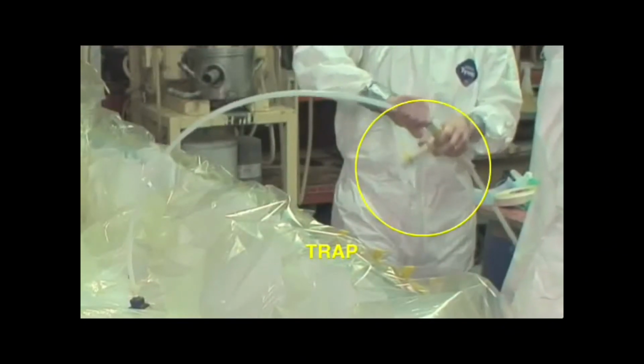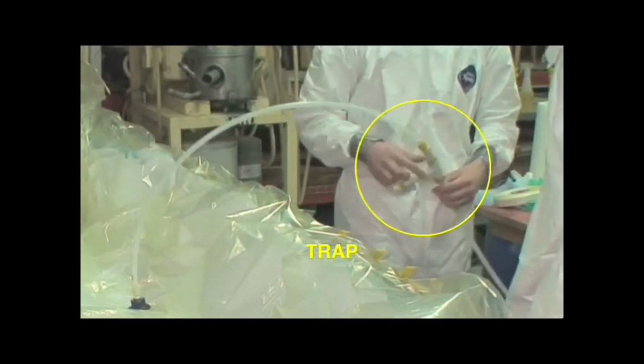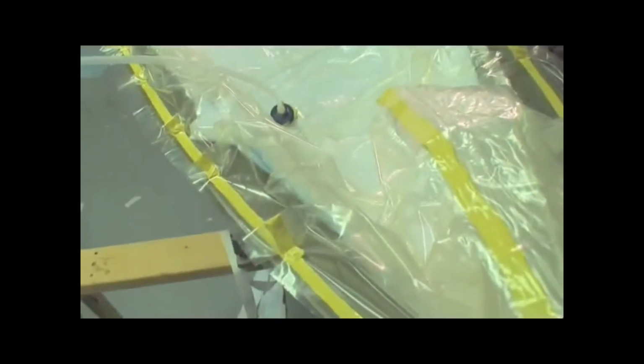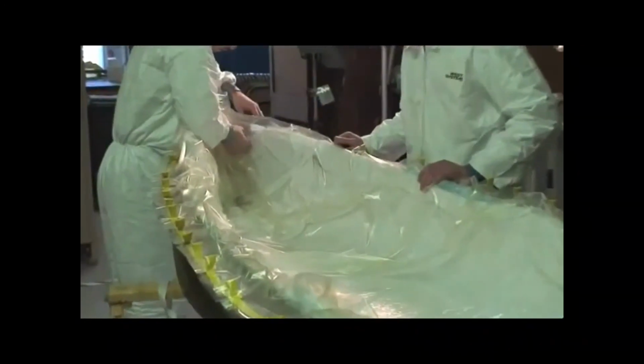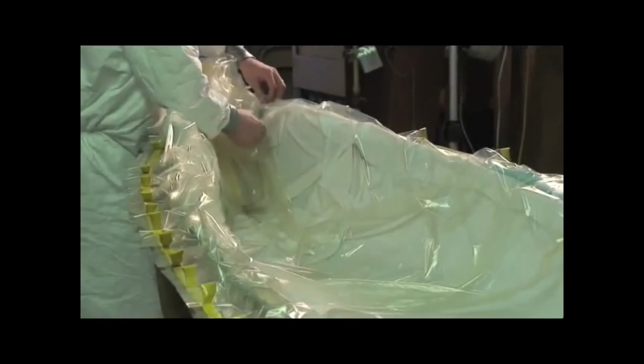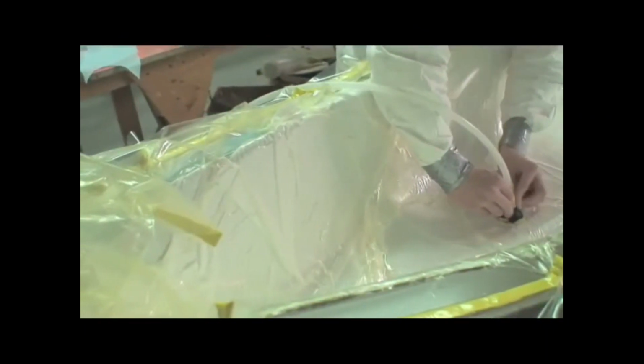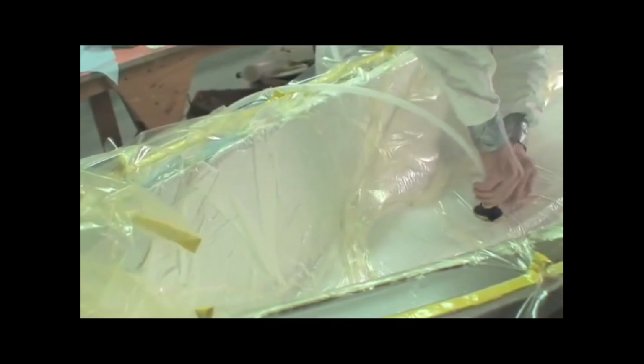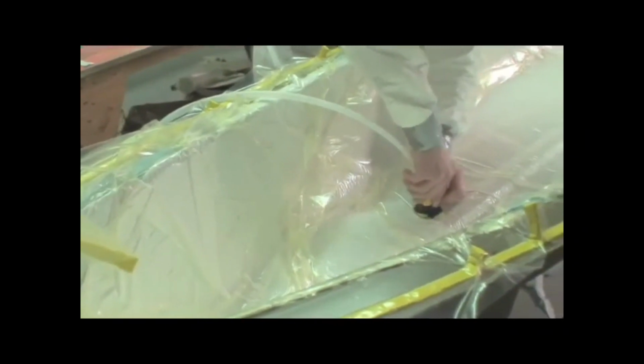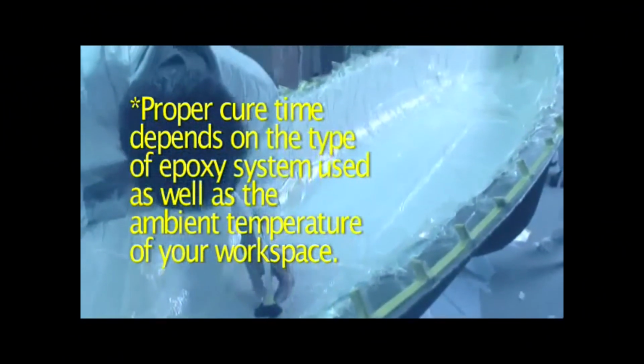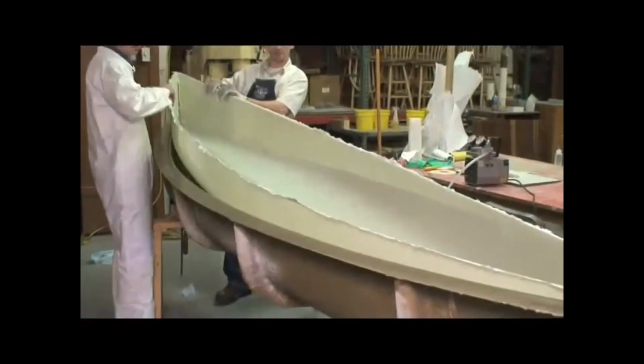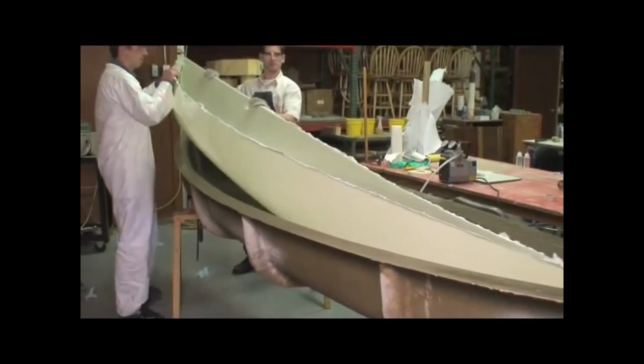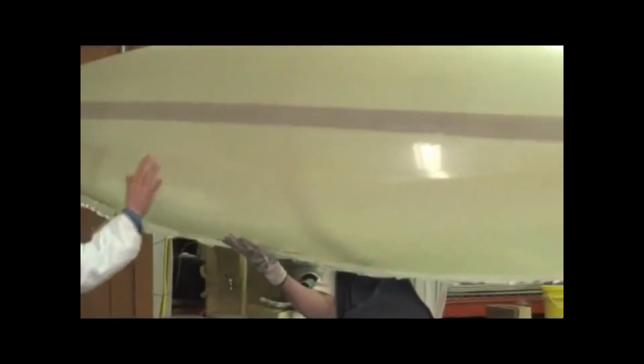A trap is put in line with the vacuum tubing to catch any excess resin before it goes into the pump. The air is evacuated from under the bag and a vacuum is generated. As the bag is evacuated, it is important to position it to avoid bridging in any tighter spots. If you have any leaks, fix them with vacuum sealant tape. Once the part is under vacuum, don't remove the bag until the part cures. After the part is cured, remove the vacuum bag, breather fabric, and peel ply and pull it from the mold.